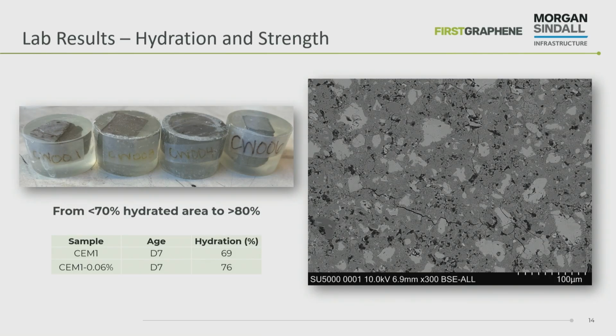So really, we did some in-depth investigations into the cement paste. We took graphene and cement and water, and that's it. That's all that's in these samples. This was just an SEM, so we wanted to see what the effects of clinker hydration and graphene had on the hydrated area of these images. So we just took the cement paste, polished it, infused it with resin, and polished it again, and so we get images like this on the right, very flat cross sections of the cement paste. You can see on the images the unhydrated cement particles, the lighter parts of the image, and then you've got the holes, which are the dark parts, and then you've got this intermediate hydrated area.